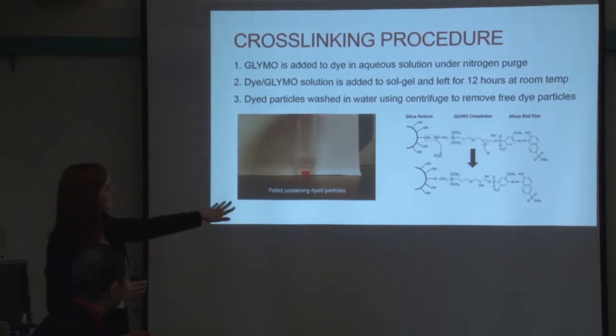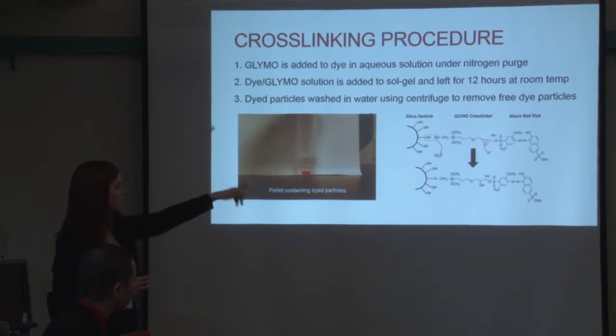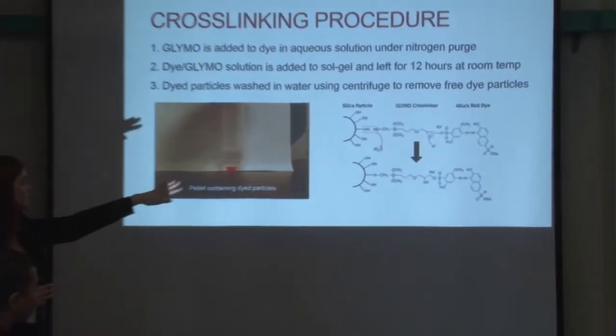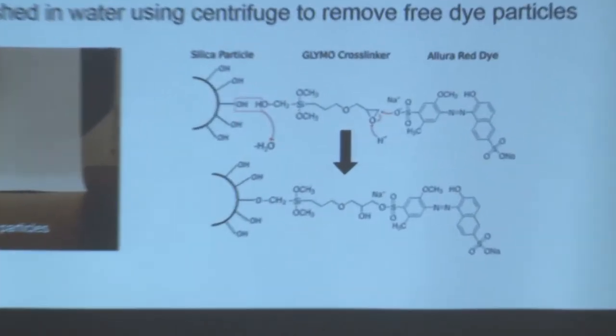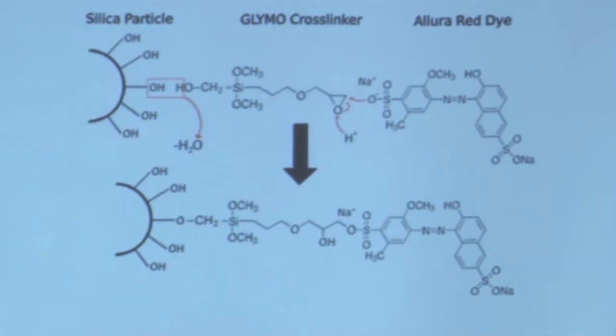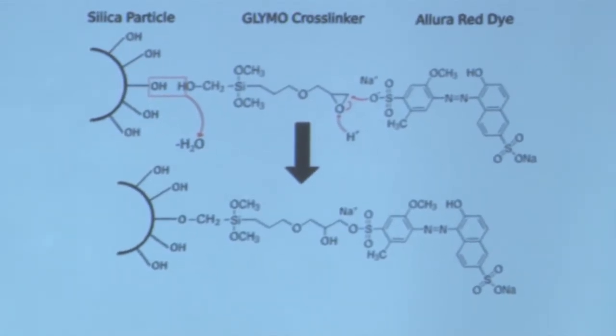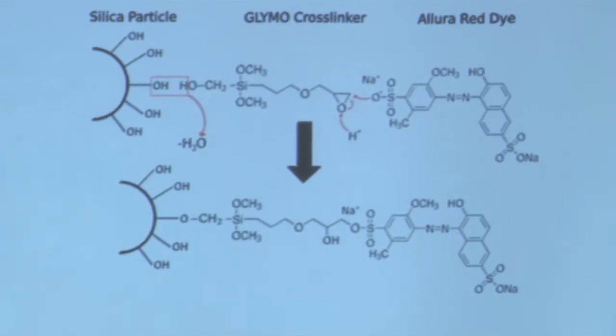So this is the chemical equation for what's going on. First we have the nucleophilic substitution between the Allura Red dye's sulfonate group and the epoxide group of the glymo crosslinker. And then we have the silane group undergoing a condensation reaction with the hydrolyzed silica precursor.